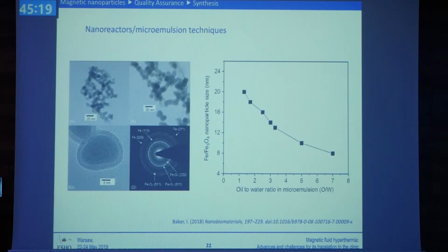This means, for example, that depending on how much of the oil phase you have compared to the water phase in your microemulsion, you can create iron or iron oxide nanoparticles that range in size, even from 8 nanometers up to 20 nanometers. The good thing about these techniques is that the nanoparticles you get not only have a controlled size, and as I will tell you later, size matters. They don't only have a controlled size, but they can also have a small dispersion. So the nanoparticles you create are around a median value of radius, and they have a very small dispersion around it.